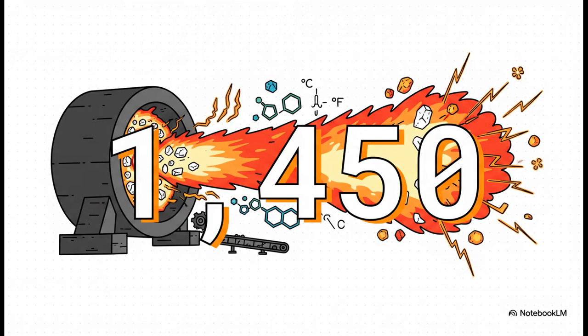Now, I really want you to notice the sheer intensity of that 4th step we just looked at, the kiln firing. Inside that massive cylindrical rotary kiln, which, by the way, can be up to 200 meters long, the materials are subjected to a roaring flame. The temperature reaches a staggering 1,450 degrees Celsius. That is roughly 2,640 degrees Fahrenheit. Just mind-blowing heat. This is the extreme sintering temperature required to force those crushed rocks to chemically combine. It's an incredibly demanding, energy-intensive environment.